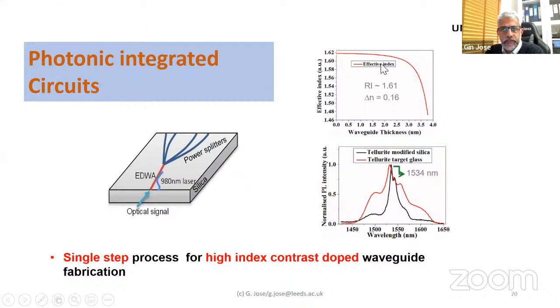And the application of this, as I mentioned, is that we can increase the refractive index at the surface of the glass. So you create a layer of higher refractive index. That can be used, say, to fabricate waveguides doped with rare earth ions and complex photonic circuits using that glass surface. It can also be put on, say, silica on silicon materials as well.